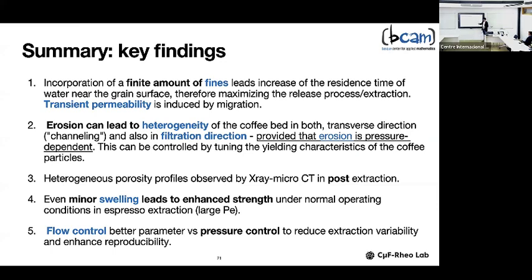Erosion can lead to heterogeneities in the transverse and the normal direction. In the filtration direction, heterogeneity is developed only if you have a model which depends on the absolute value of the pressure. So different pressurization between inlet and outlet will lead to different erosive patterns. We have observed some evidence, although to be 100% honest, we should continue to do other experiments, also with the swelling, to exclude other possibilities. But I think that one possible explanation is that the pressure environments affect the adherence of fines to the largest coffee particle, and therefore introduce this pressure-dependent erosive pattern.